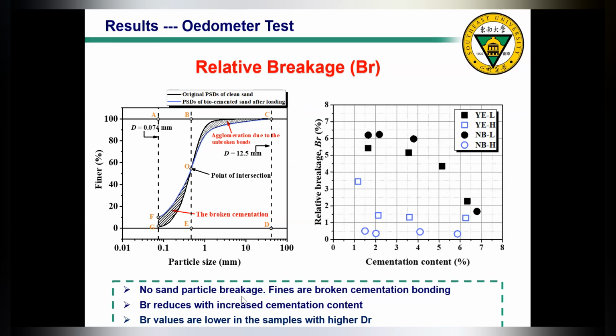However, with increasing cementation content, the BR value reduces significantly. It means that if we have a lot of cementation content, the breakage of cementation bonding will be less severe. And also, we find that with the increase in the initial relative density of the soil sample, the BR values are also lower. That's because, for initially high relative density samples, the interparticle bonding or cementation are more likely to locate in better places to form better bonding. So the relative breakage will be smaller.